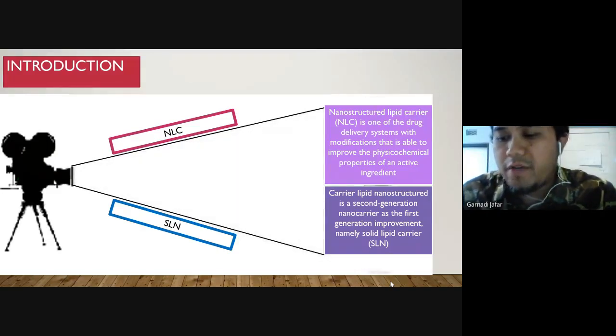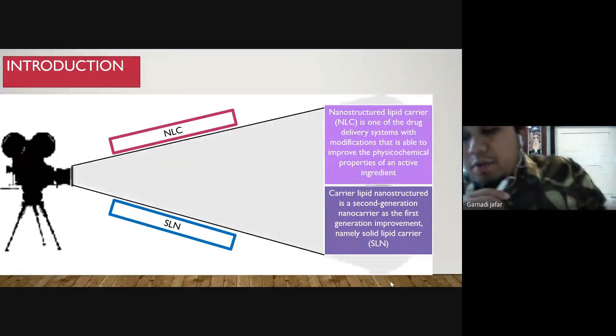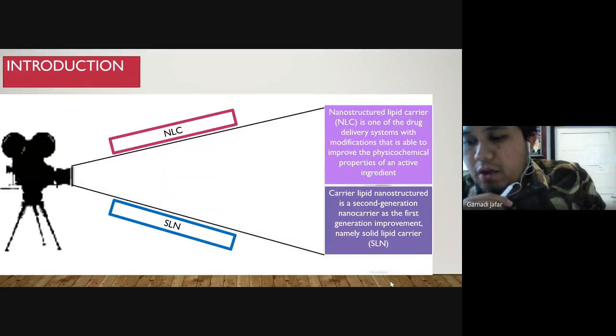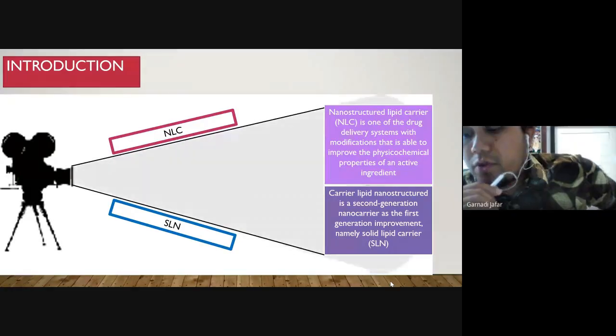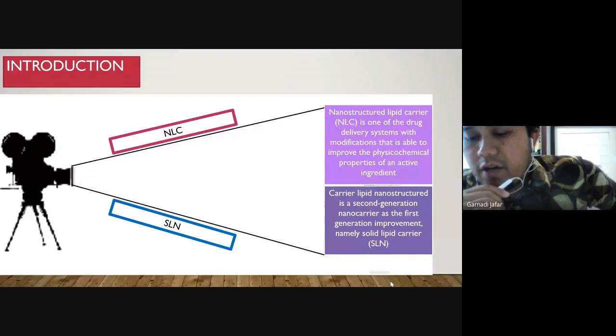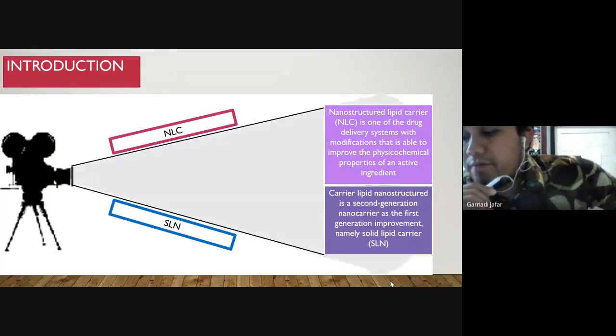The weakness of SLN is that the matrix structure formed by SLN is very solid, resulting in low loading capacity and the possibility of expulsion of the drug during storage. This system also has a high potential for expelling the drug. The liquid lipid component in NLC functions to overcome the SLN weakness, namely to disrupt the conformation of the solid lipid matrix so that it does not become a perfect solid lipid crystal.